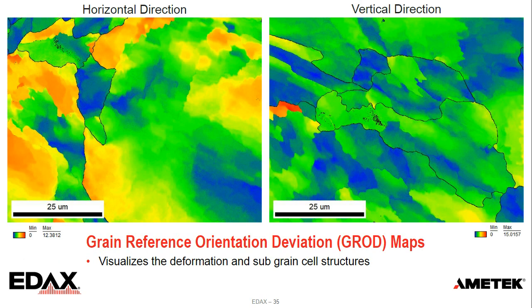One is what we call a GROD, or Grain Reference Orientation Deviation map. So in this case, we calculate a grain, like we showed earlier. We determine a reference orientation. There's a number of ways we can do that. And then once we have that reference, we can shade each point within the grain as far as misorientation from that reference. And you can see, the black lines on there are the determined grain boundaries. So it gives us some idea where the grains are located.